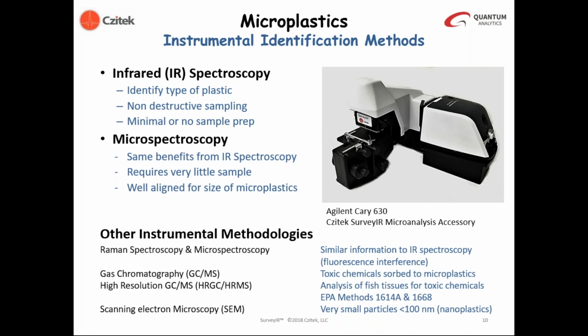Gas chromatography mass spectroscopy is a trace method. In its normal implementation, one could not identify the identity of the microplastic, but can analyze at a trace level any other chemicals that are adsorbed into the microplastic material. Special technology in GC mass spec using higher resolution mass analyzers can also be used for the analysis of tissues of organisms. And then finally, scanning electron microscopy can analyze extremely small particles, but the molecular information from the plastic is not determined in scanning electron microscopy. With energy dispersive X-ray, one can get an elemental signature from the plastic, but not a molecular one.